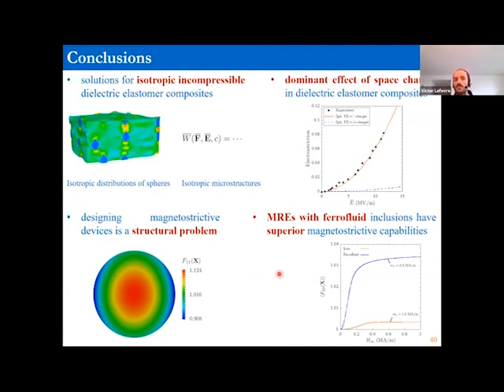But you can also use these models in a kind of reverse way, where you can compare your results with experimental data. And if they don't agree, it means that you are missing something important. You can identify that phenomenon that's missing, as well as use the models to probe the specifics of these very complicated, very small scale phenomena that might be otherwise very difficult to probe experimentally. So it's good to keep in mind that when looking at these composites, there's really these forward and reverse ways of looking at things, and both of them have their benefits, and it can be very nice to do.